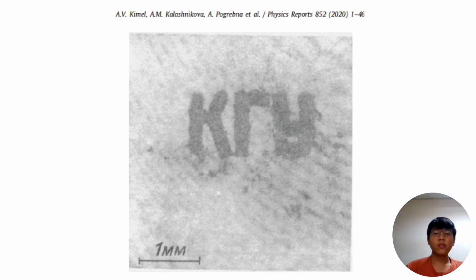You can see from this graph, by using a Kerr microscope, three letters K, R, Y are stored on this film because polarized light creates different magnetization directions compared to the other unilluminated parts. So this is basically the first research about photomagnetic recording. And this is all my part. And the next part will be theory. Thank you.